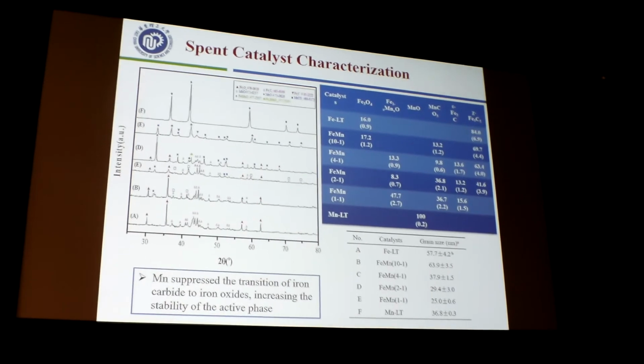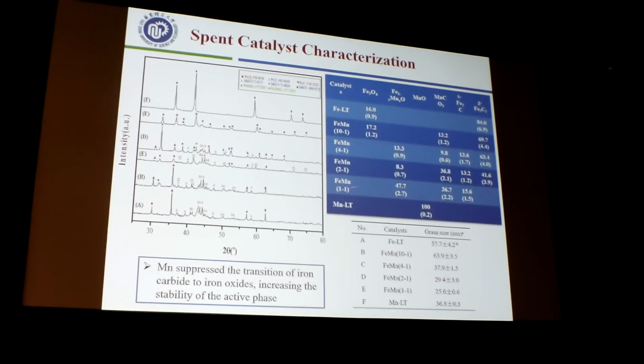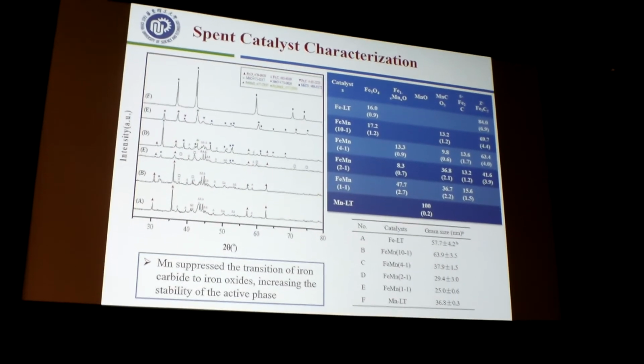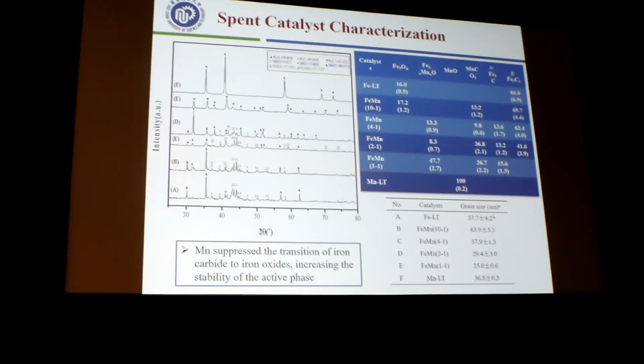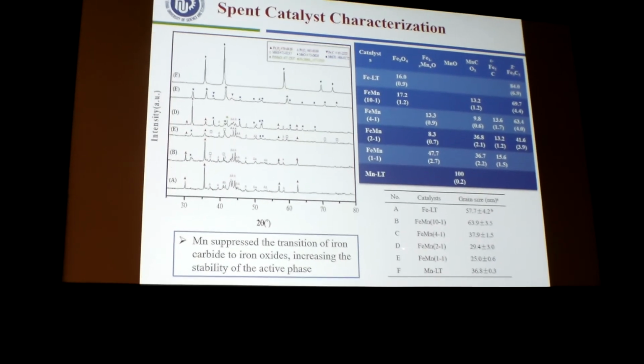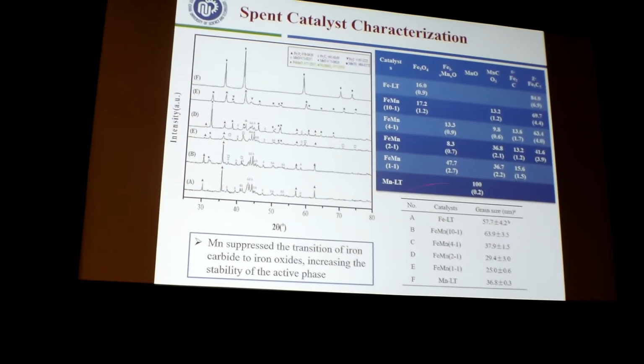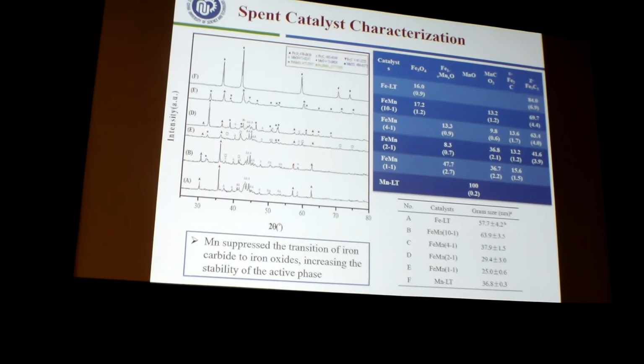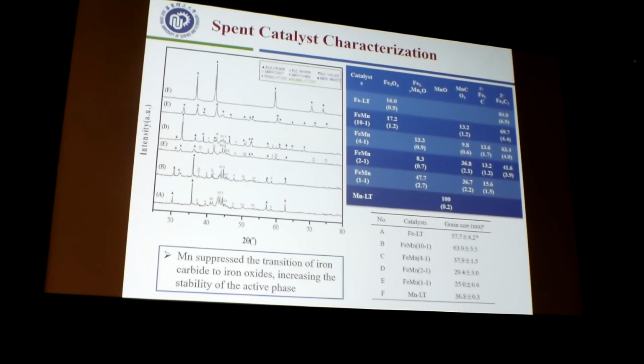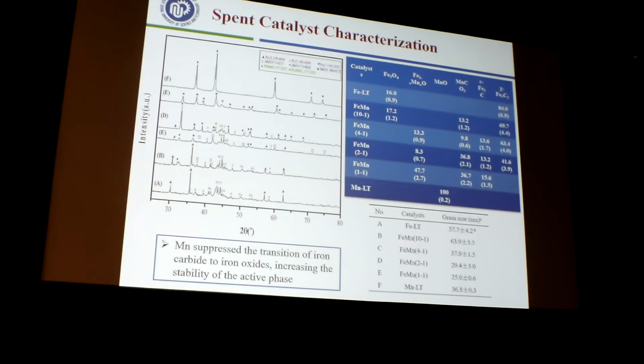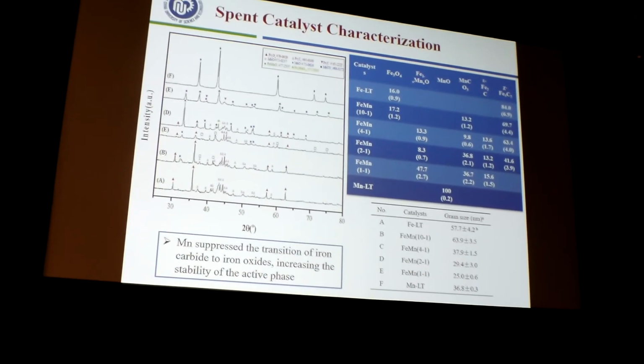So for the spent catalyst, we also did the XRD characterization and the BET and the particle size measurements. So basically, the enlargement of the grain size was observed, but as the loading amount of the manganese increases, the particle size also showing a decrease in trend. As we can see in the XRD pattern, the manganese suppressed the transition of iron carbide to iron oxide, which means that the manganese can increase the stability of the active phases.